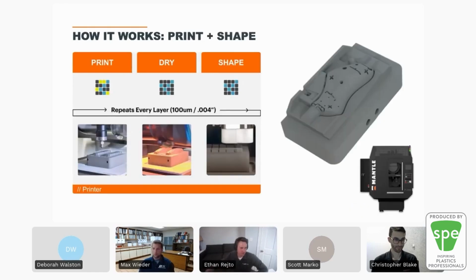Inside of our printer, which you can see here in the bottom right, every single layer, we lay down a layer of this paste, a very small layer, about 100 microns thick. We're just extruding the material out of a needle. Since it's viscous enough, we don't have to heat it or anything like that. We dry every single layer to firm it up a little bit. This actually removes the solvent.